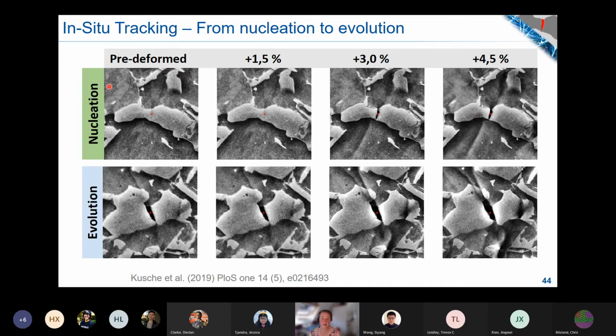So we get a lot of these nucleation images or sequences rather than just a few. And we can also, of course, look at evolution for a lot of sites, as you would always do. What we found was what we expected, that 2D imaging long-term won't be enough to understand the mechanisms, because actually you end up looking at sites like this and then you get half of them which evolve and form bigger cracks as you would expect, and there are a lot of them which don't do anything at all. So clearly the stress state has changed a lot by first deforming a material and then polishing the surface, right? We knew that to start out with.